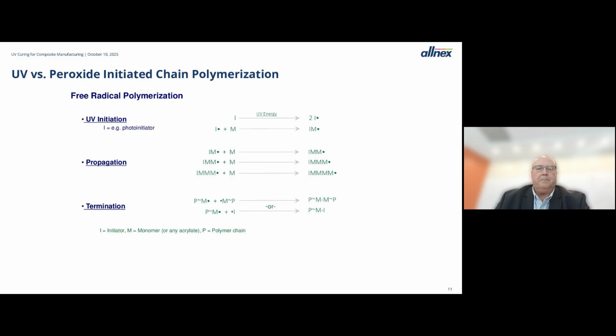With UV, it's pretty much the same process. It just starts differently. With UV, you'll have a photoinitiator instead of a peroxide. That absorbs UV energy and breaks into radicals. And those radicals do the same thing. They'll add to a monomer and then propagate as you add more and more monomers onto the growing polymer chain, and finally terminate when you get two radicals coming together.